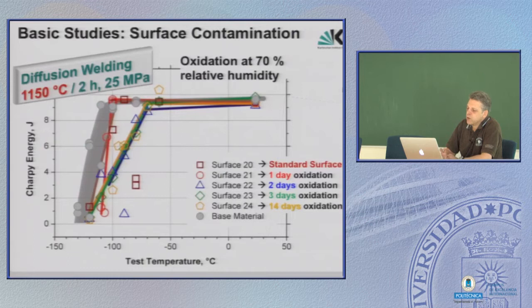The next step was to see how oxidation of the surface influences diffusion welding. So we again use the best performing surface, that's called standard surface for now, and put the Eurofer plates in a relatively wet environment. Oxidation at about 70% relative humidity was done for 1 day, 2 days, 3 days, and 14 days. We compared it with the base material. We increased the welding temperature a bit to 1150 C, performed the welding for 2 hours with a, let's say, low pressure, 25 megapascal, and again compared it.